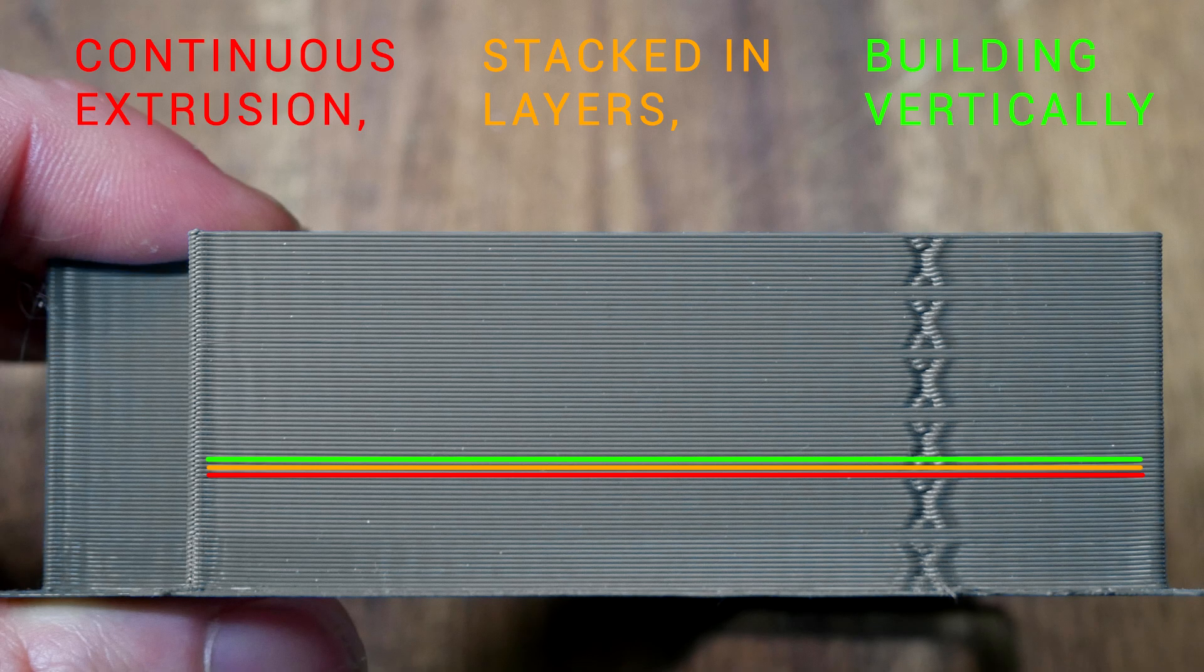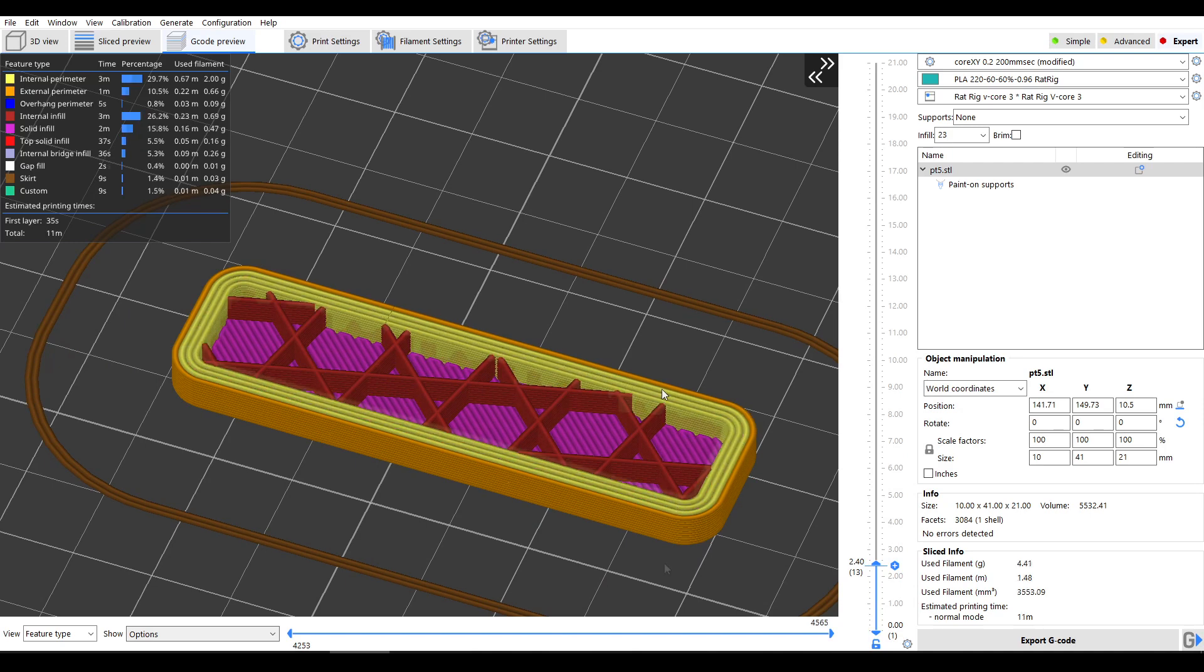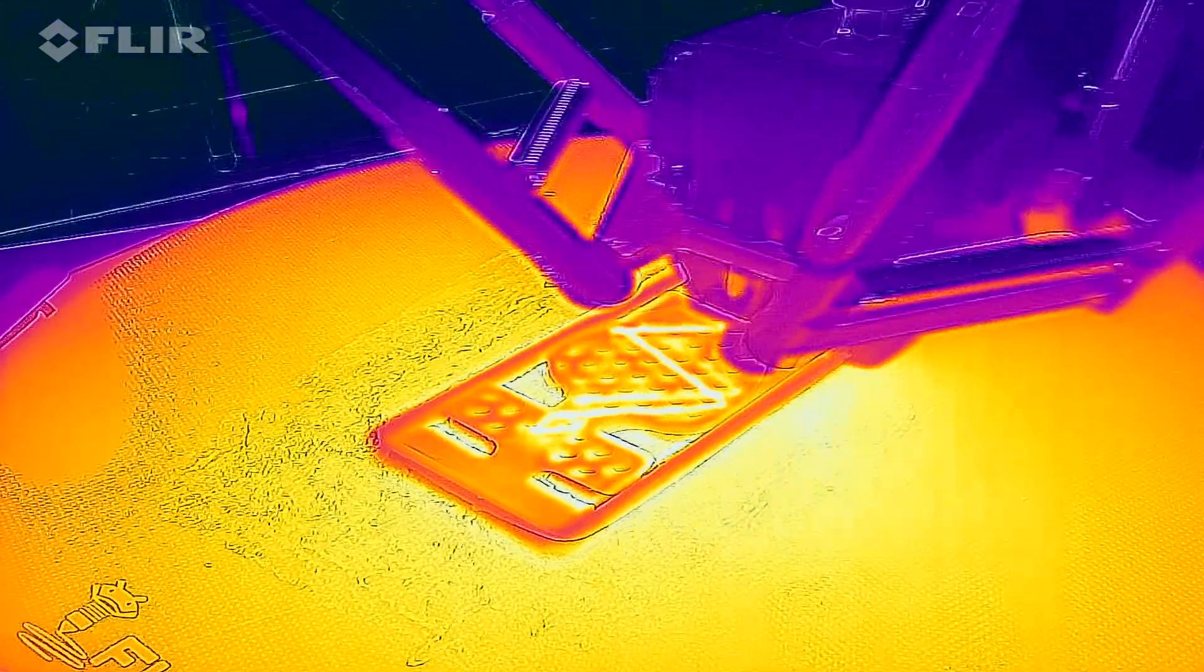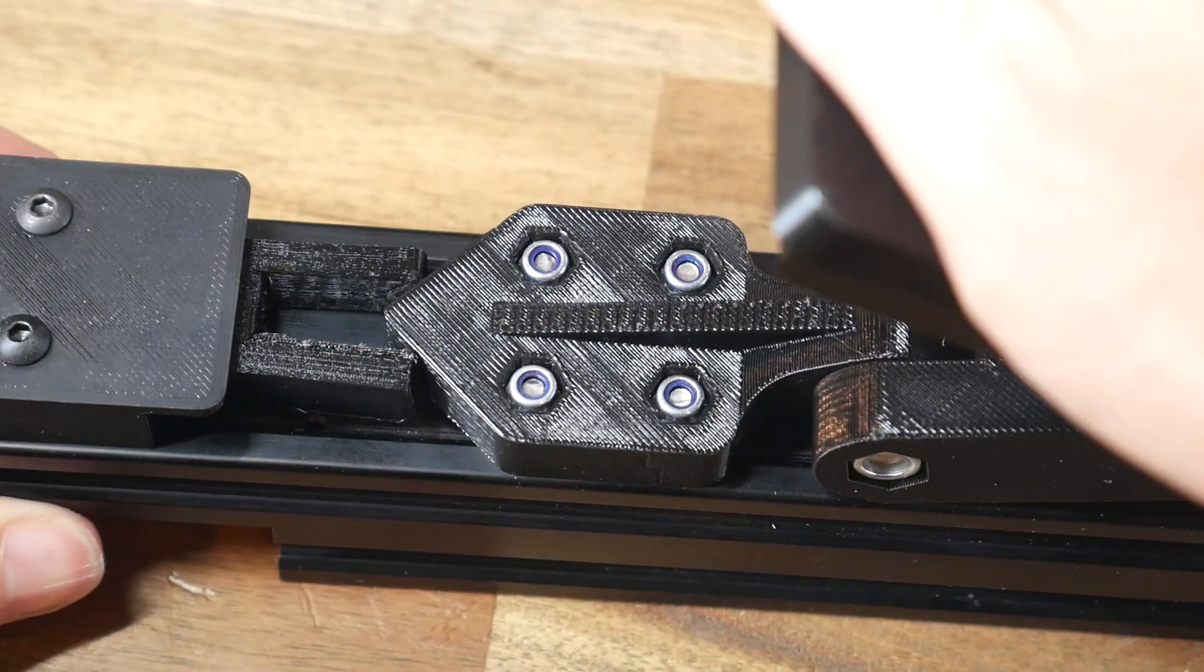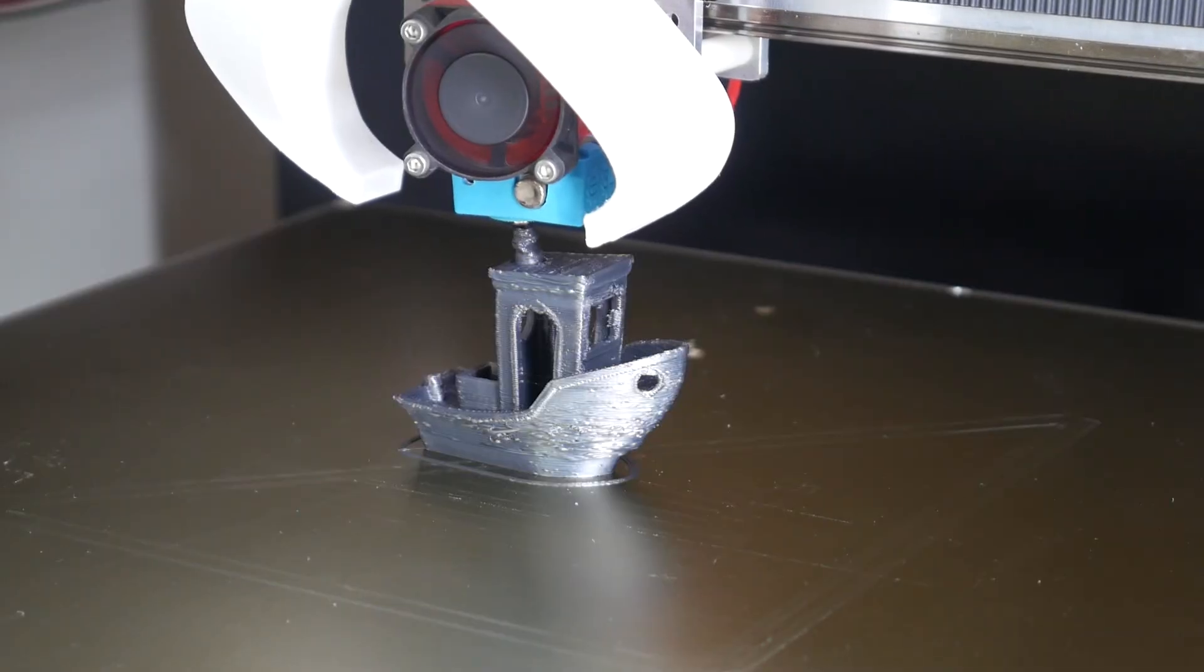But one area that hasn't received this magic bullet is the compromise between strength and quality. 3D printed parts are made of continuous plastic extrusions, stacked vertically on top of each other in layers. We can increase the strength of these continuous extrusions by increasing the amount of perimeters, their width or increasing the density of the infill. But that won't address the main weakness of 3D prints, in that the layers stacked on top of each other are quite easy to split apart. The interlayer or vertical weld strength of the layers is largely dictated by hot end temperature, combined with part cooling and feed rate speed. And these parameters are what the power test piece and Kraken will allow us to test.